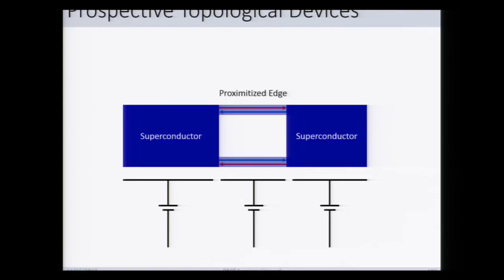So how can we think the density is the same in the normal state and the superconducting state? Yeah, that's a good question. Even to measure a Hall effect in the superconducting state, you have to first kill superconductivity with a magnetic field and then measure things. Maybe if you do a quantum capacitance measurement, you could imagine doing something like this, but we haven't done such a thing. The way to think about it is, you put a density of 5 times 10 to the 12 in the normal state, and you cool down, and it becomes a superconductor. Now, the density may or may not change, but you're making the same comparison with any other material. The density is always determined in the normal state, and then you cool down. So you're quoting the density in the normal state for which, when you cool down, the system becomes superconducting.